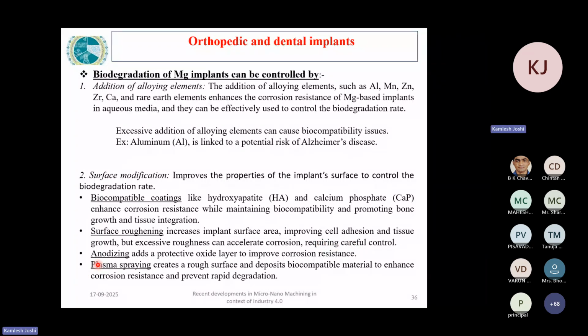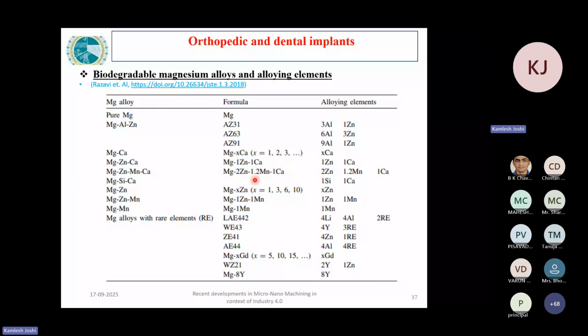We can do anodizing to add a protective layer over the surface. Another way is to use plasma spray to create a rough surface and deposit compatible material to enhance the corrosion resistance and prevent rapid degradation. So these are some of the ways which can be used to improve the biodegradation of magnesium materials.